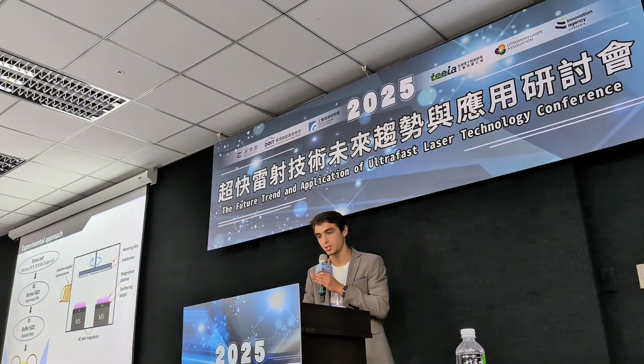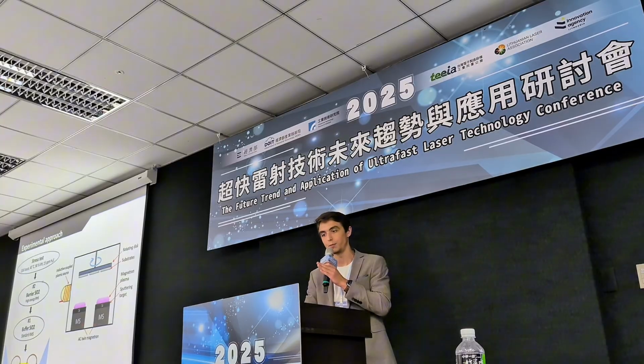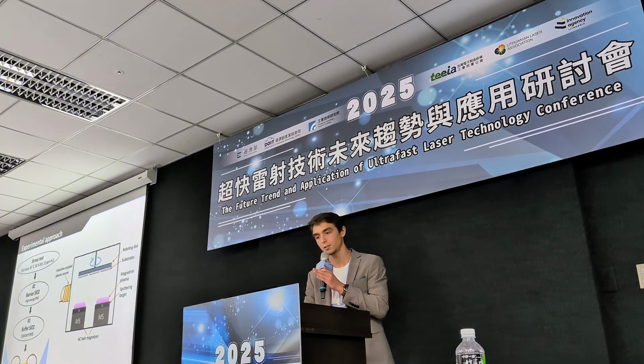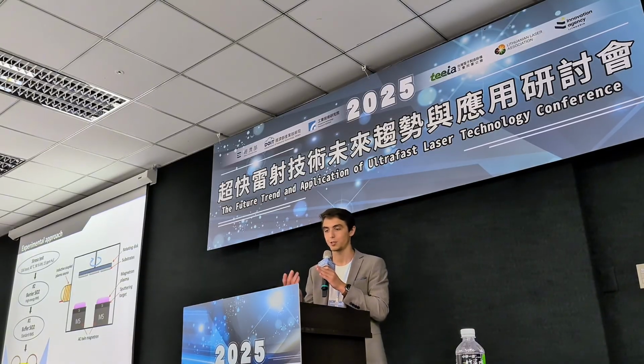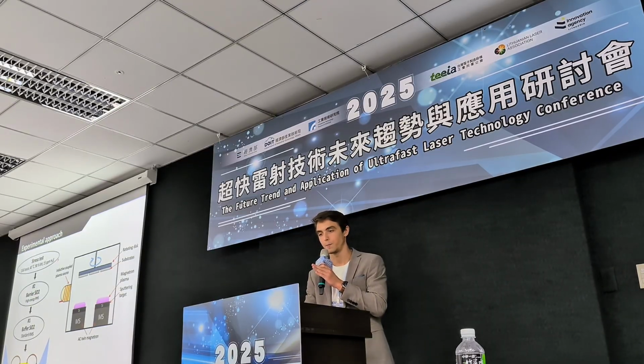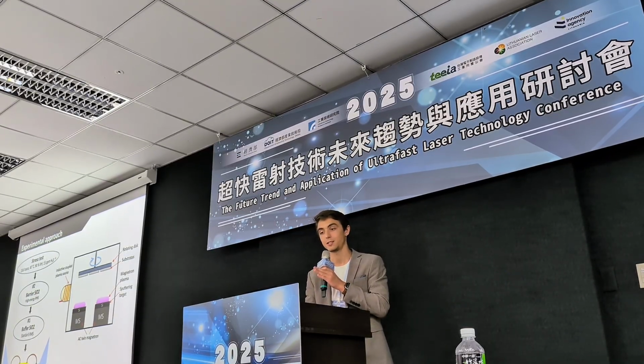Then, after the soft buffer layer, we apply the barrier layer of high density. For deposition of such a barrier layer, we need to use more aggressive regimes that by themselves can damage the LED. But such aggressive regimes make sputtered atoms distribute over the developed structure of the LED and increase the density of the coating. Technically, this barrier layer is responsible for protecting the LED from the stress test.